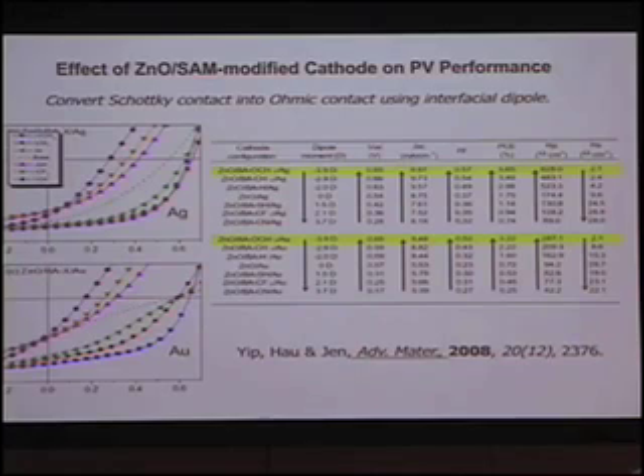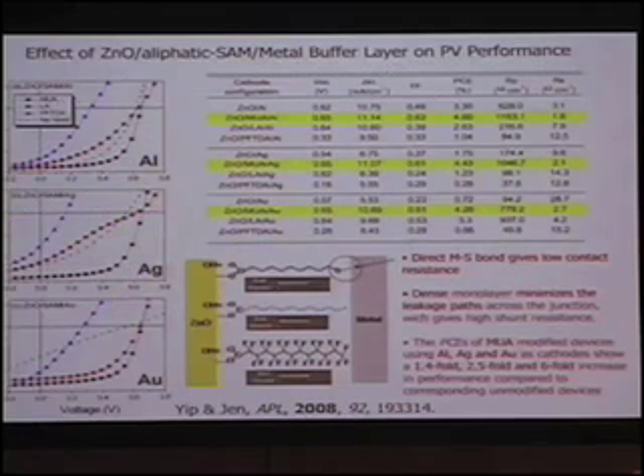When we observed this, we were quite excited. But then we were actually stunned by the discovery that instead of the conjugated SAM, an aliphatic SAM actually provides even better results. If you look at the SAM here, especially this double-ended SAM, one end you can link with zinc oxide, and on the other end you can form bonding with gold or silver at this interface. As a result, you can greatly reduce the series resistance, and you also terminate a lot of interface traps. As a result, you can have very high shunt, or parallel, resistance.